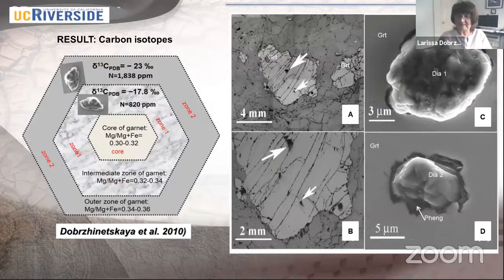So, okay, now we summarize this data. I show you, for example, this garnet, one crystal, where we found several diamonds. This diamond, this diamond, this diamond, okay? We show this diamond here in high magnification. The bar scale is 3 micron, and the bar scale of this garnet is 4 millimeters. This is part of the same garnet magnified. So what we found, we summarize the data. We found also that the garnet has a chemical zoning, okay? The chemical zoning shows different magnesium content in the core, and then zone 1 and zone 2.